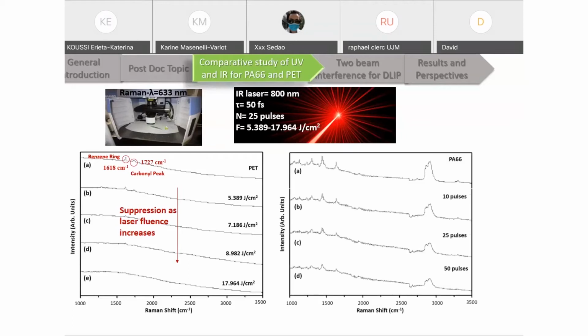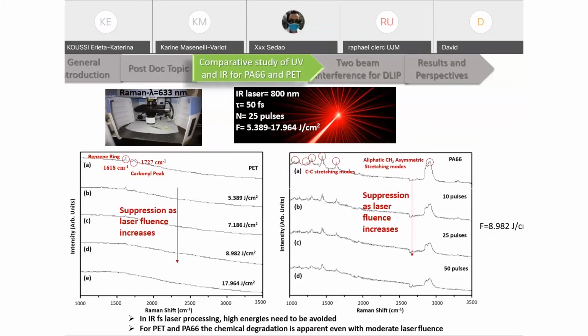For the PA66 sample, we have decided thus to optimize our analysis by testing now an increasing number of pulses and maintaining the IR laser irradiation at a moderate laser fluence of 8.9 joule per square centimeters, but still increasing the number of pulses. Here are the characteristic peaks. And now by increasing the number of pulses, we have also observed the suppression of the peaks as the laser fluence increases. So the general remarks from this analysis is that in IR femtosecond laser processing, the high energies need to be avoided. And for PET and PA66, the chemical degradation is apparent even when we have a moderate laser fluence.